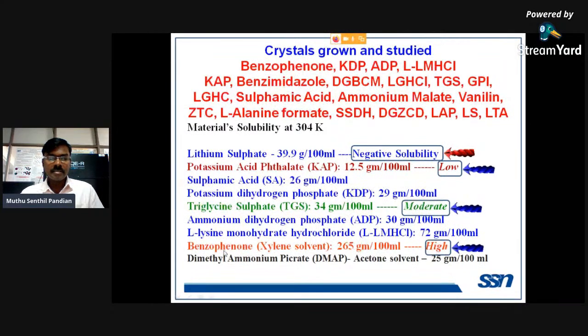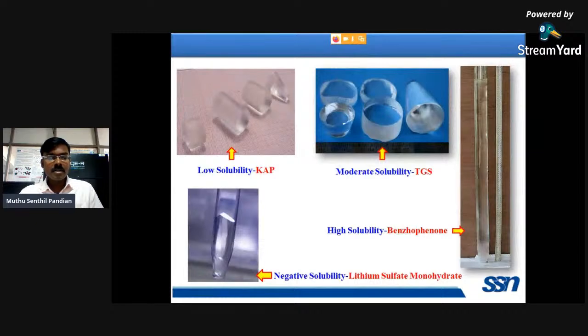We have selected these benzophenone single crystals for the longest solution crystal. So we can grow organic crystals, semi-organic crystals, inorganic materials, positive soluble, negative soluble. Anything is possible in this SR method. So this is the low soluble KAP single crystal, this is the moderate soluble TGS single crystal, and this is the highly soluble benzophenone single crystal, 850 mm longest crystal, and this is a negative soluble lithium sulfate single crystal.